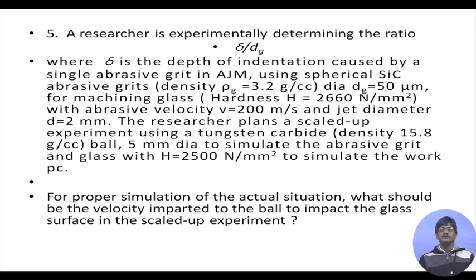The diameter of the ball is different, the density of the ball is different. Instead of density to be 3.2 grams per cc, it is 15.8 grams per cc. Instead of diameter 50 microns, it is 5 millimeters, much higher, and the glass also is, instead of 2660, it is equal to 2500. So, how can we possibly simulate? The answer to this is, since he is finding out delta by dg, mind you, let us see what value the velocity should have, so that delta by dg comes out the same in both cases.